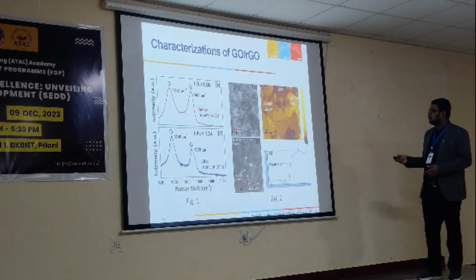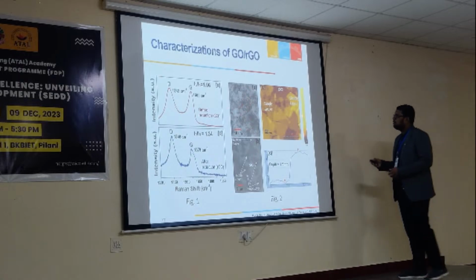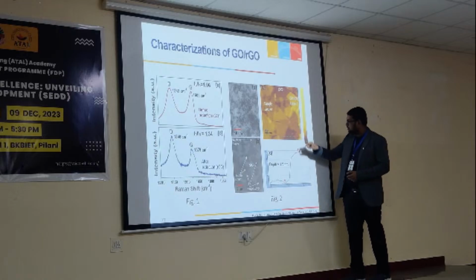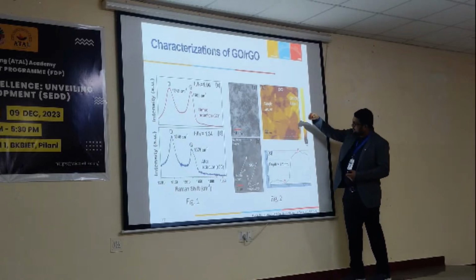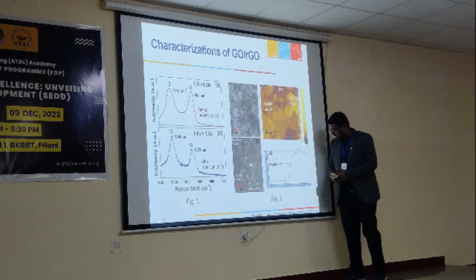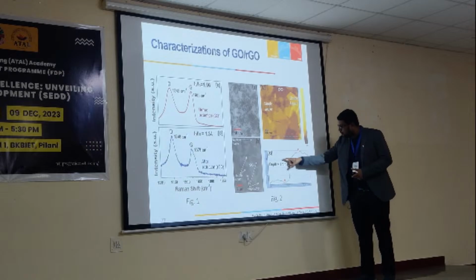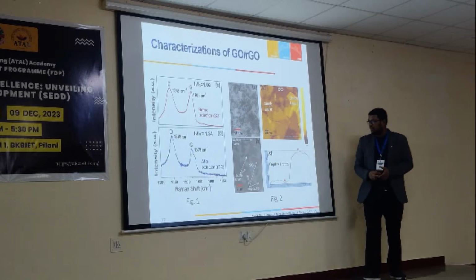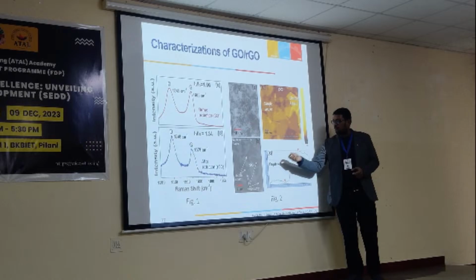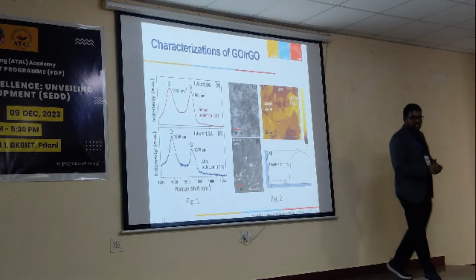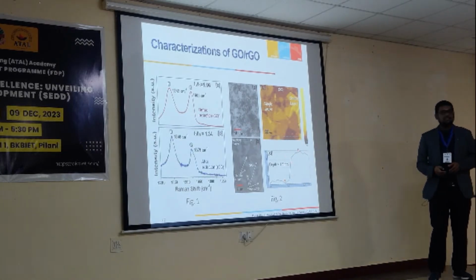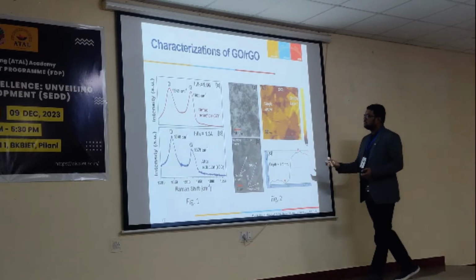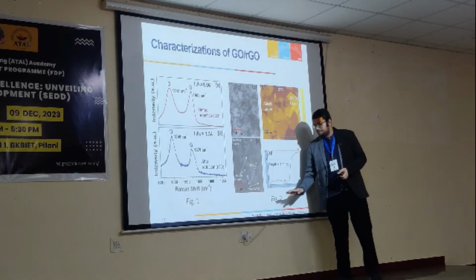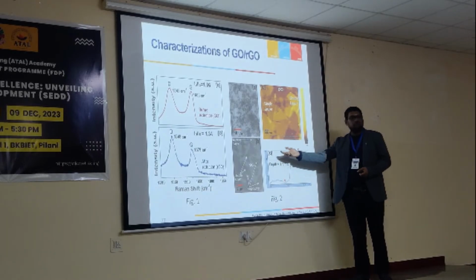This is called atomic force microscopy. This is the scanning electron micrograph. This is the atomic force microscopy. We can see this portion. Suppose the atomic force microscopy tip is moving from here to here, and due to this tip transition, we have measured a depth of 1.5 nanometer. So graphene oxide, a one atomic layer thin layer, is showing 1.5 nanometer. This is because we have the oxygen functionalized groups at the top and bottom. That's why this thickness is slightly more than one atomic layer.